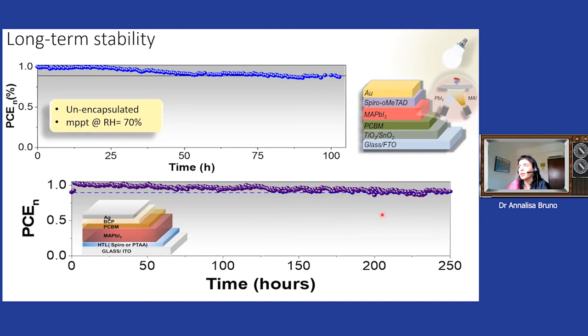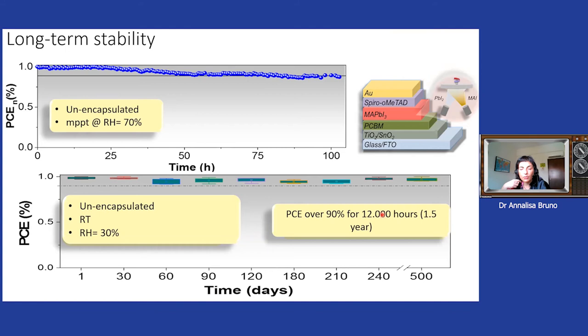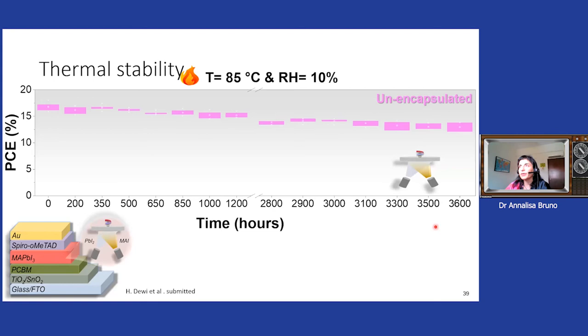And very nice, when samples are stored at ambient condition and just measured from time to time, so they are not continuously illuminated, they have shown very good stability, maintaining over 90% of their performance for over 1.5 years. So this is extremely promising for commercialization.